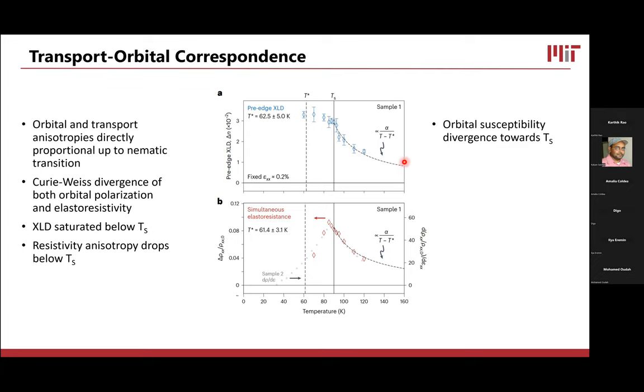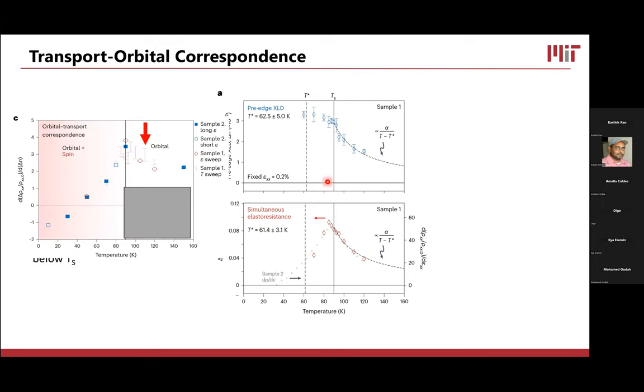Now, as the XLD diverges, the resistivity anisotropy also diverges. And the ratio of the resistivity to the XLD stays roughly constant above the nematic transition. Below the nematic transition, the XLD under large strain stays saturated while the resistivity drops. So if I put this data on my phase diagram, these points correspond to these open brackets. Above the transition, it's roughly in the same ballpark value. And below the transition, it drops rapidly.